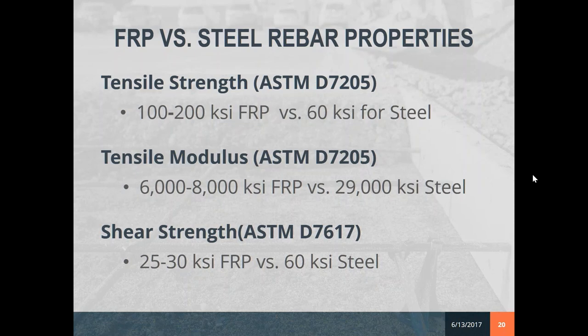And these are perfect applications for flat work, hike and bike trails, sidewalks, parking lots, and eventually into roadways as the industry becomes more and more familiar with them. They have been used and studied in a lot of roadways and had very good success with that. But again, you just have to understand your material properties and their applications. Shear strength is lower than steel. Again, when you're designing with your flat work, you're designing for temperature and shrinkage control. You're not designing for shear strength, but in structural applications you do, so you have to relook at that.